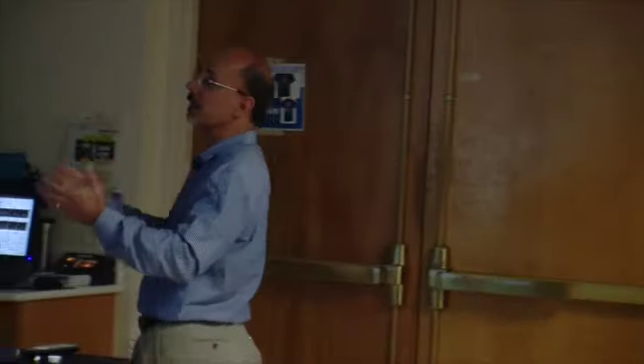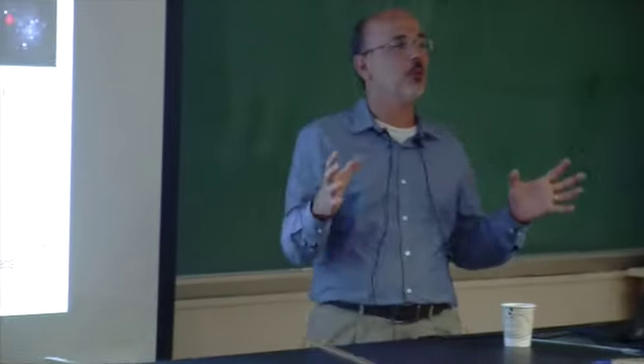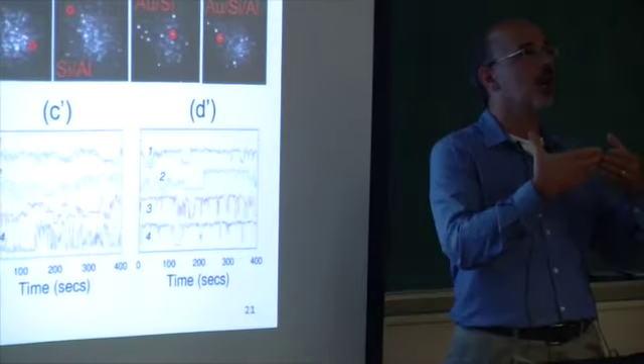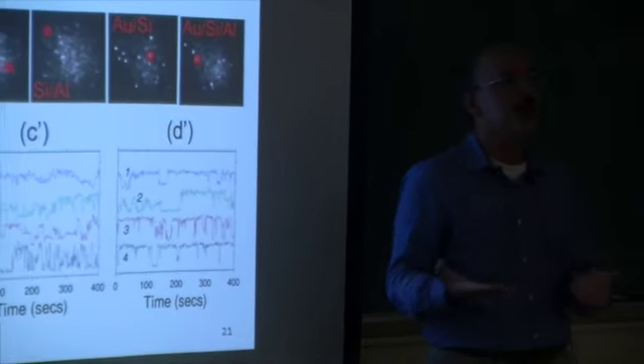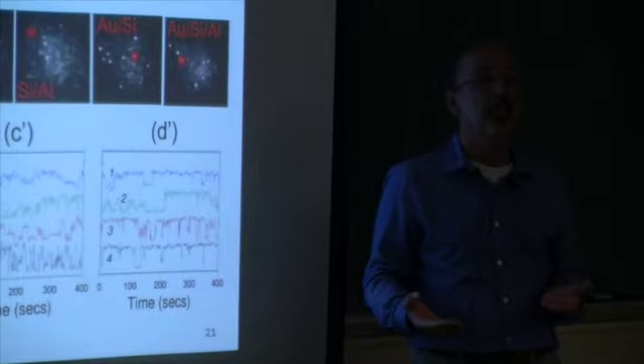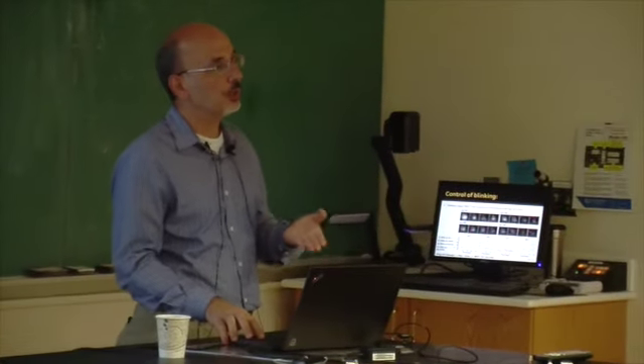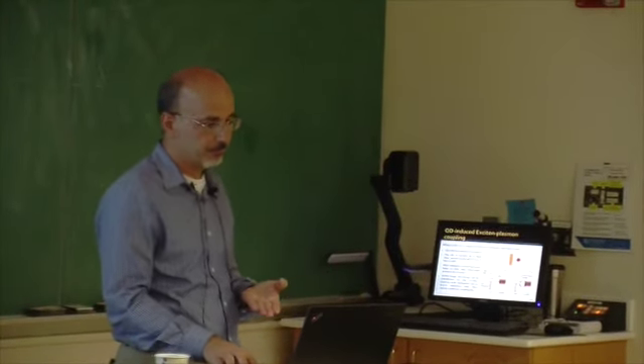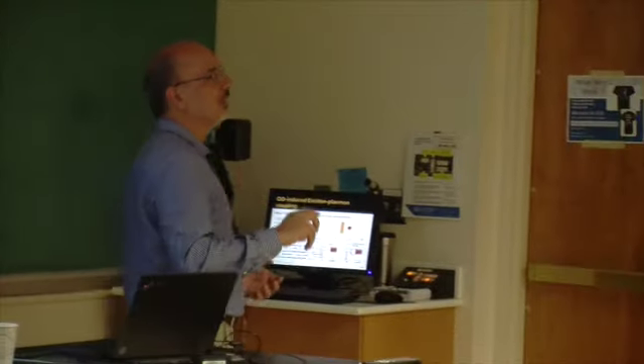But the result that you see here suggests that you can change the pattern of blinking based on the material that you put underneath. You can promote blinking if you use defects other than the defect of the quantum dot itself. Okay, I have 10 minutes to talk, and I'm not going to miss that part. So it is interesting to me.